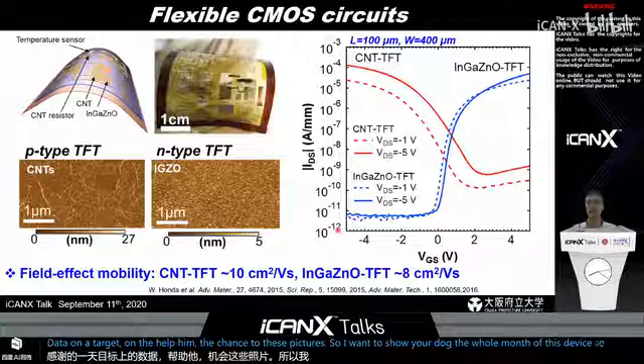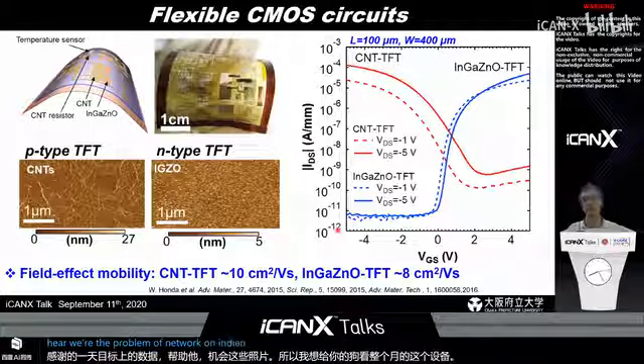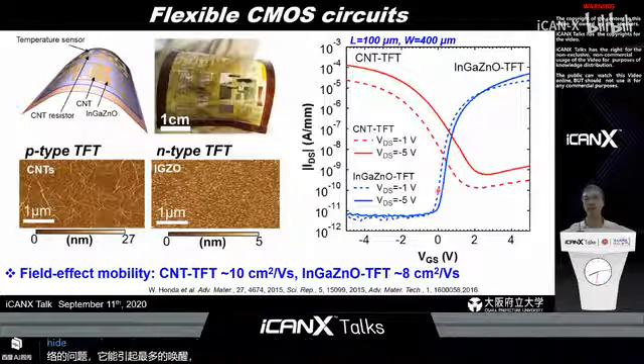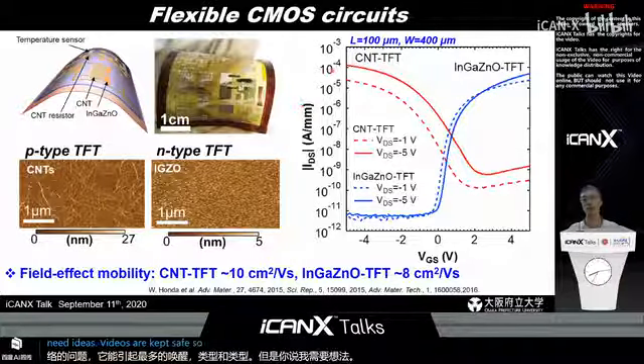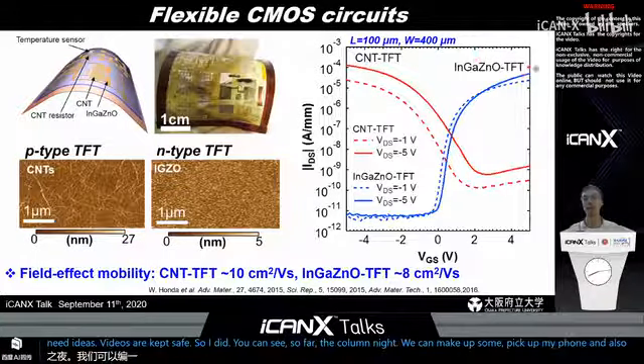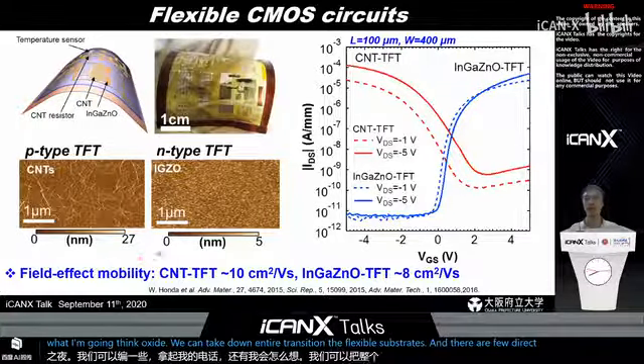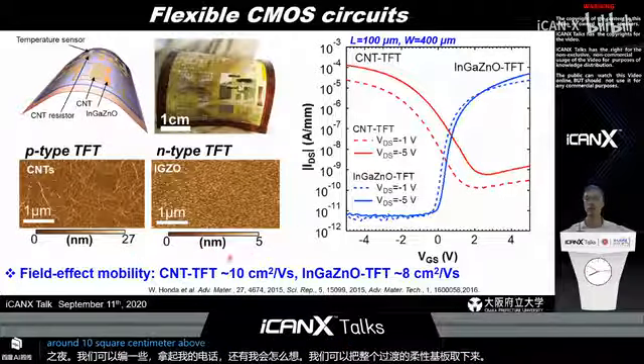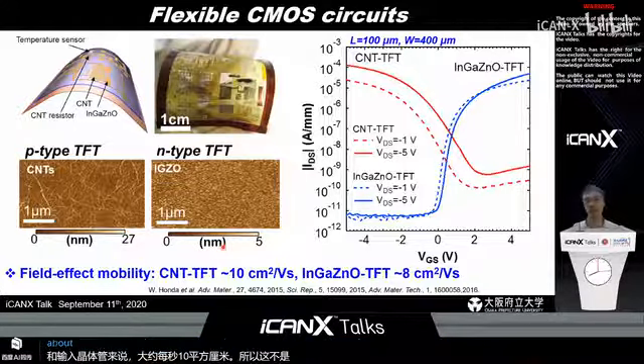Since here we use a carbon nanotube network and indium gallium zinc oxide, we can demonstrate P-type and N-type transistors. This is the IDS-VGS characteristics. As you can see, with the carbon nanotube we can make P-type transistors, and with the indium gallium zinc oxide, we can make N-type transistors on the flexible substrates. The field effect mobility is around 10 square centimeter per volt-second for both the P-type and N-type transistors. This is not excellent compared to silicon electronics. However, on a flexible substrate, this performance at that time, roughly 5 years ago, is quite good for CMOS circuits.